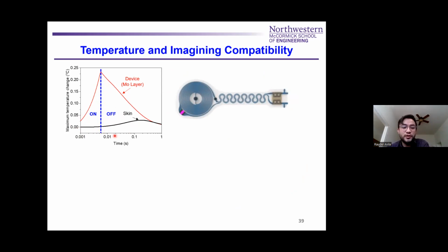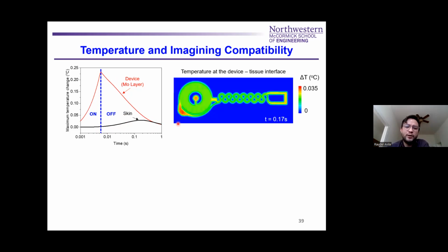And then you turn it off. So this is a very, very small time period. You can see this decrease in temperature here, and then the skin eventually catches up in this transient process. You can calculate what the temperature of your device is going to be. So you have a very, very small temperature increase here, about 0.035 degrees Celsius at the time of 0.17 seconds. It's about here when the skin temperature increases.